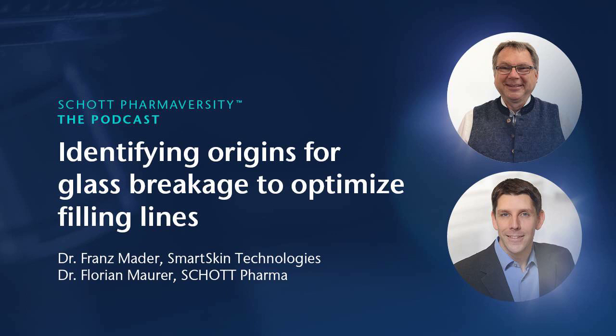From my experience, the majority of glass breakage incidences in the pharmaceutical industry follows a two-step failure mechanism, which means that the failure-inducing flaw or damages are introduced prior to and independently from the application of the failure-inducing mechanical load. It is easy to identify the second step of the failure mechanism, the place where the failure-inducing mechanical load is applied, as this is the location on a fill and finish line where breakage is observed and the fragments are found. But it is much more difficult to identify the first step, the locations where flaws are created and damages are introduced, as these locations often are not obvious.